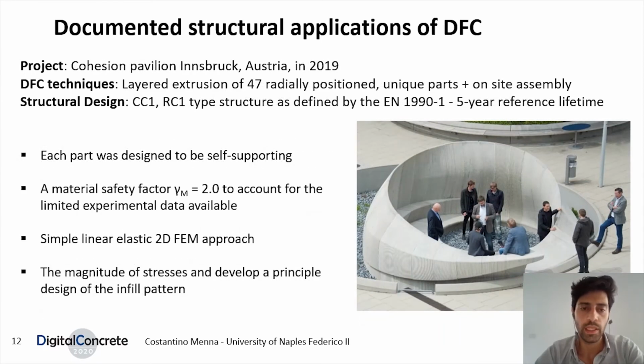Still remaining in the layer extrusion DFC technique, the Cohesion pavilion recently completed in Innsbruck represents one of the most significant examples of architectural structure. The pavilion consists of 47 unique parts with complex shape, radially positioned and assembled on site according to a predefined geometry. Even for this project, the structural design was conceived to be compliant with existing structural codes, in particular according to consequence class 1 and reliability class structures as defined by the Eurocode. The reference lifetime was 5 years.